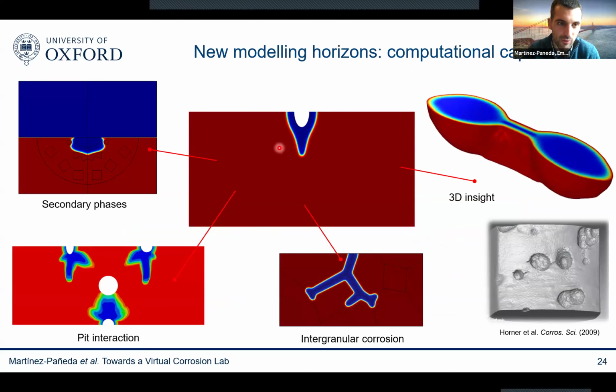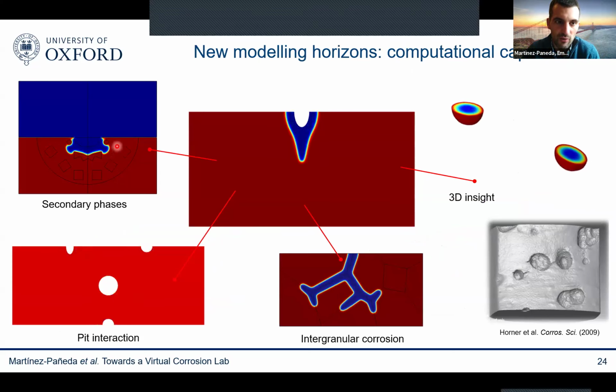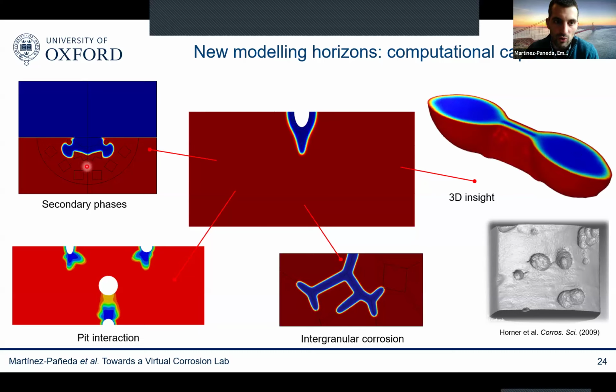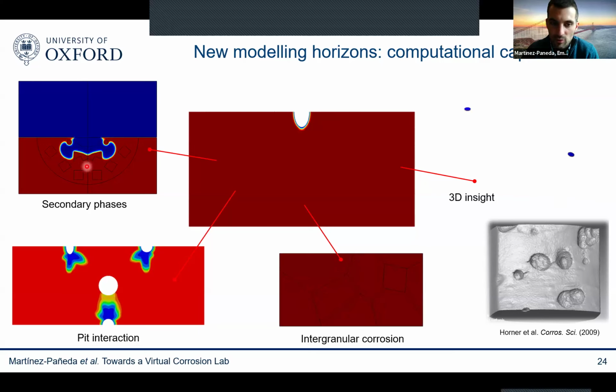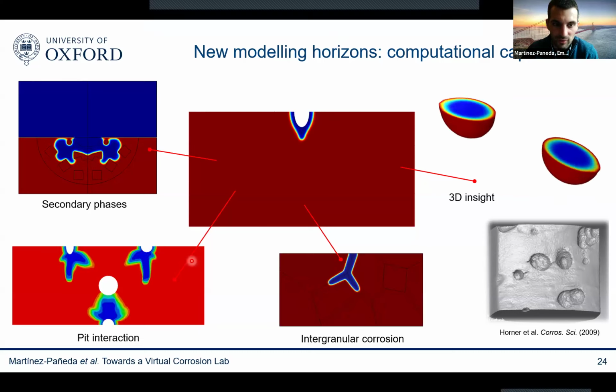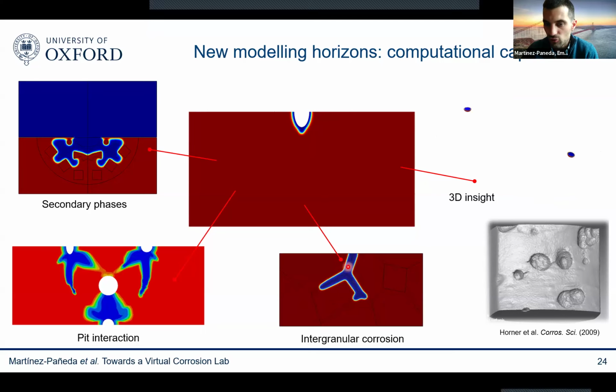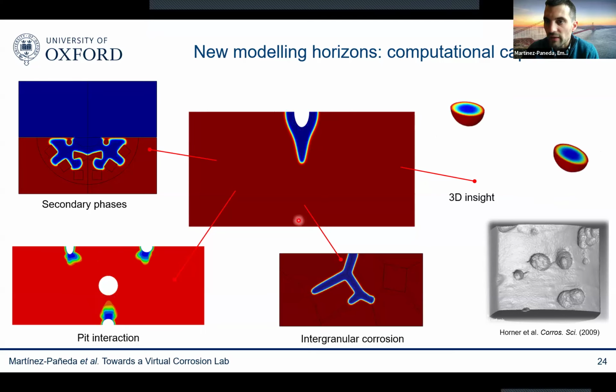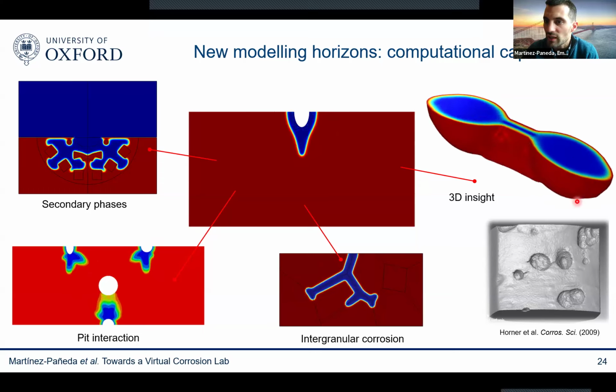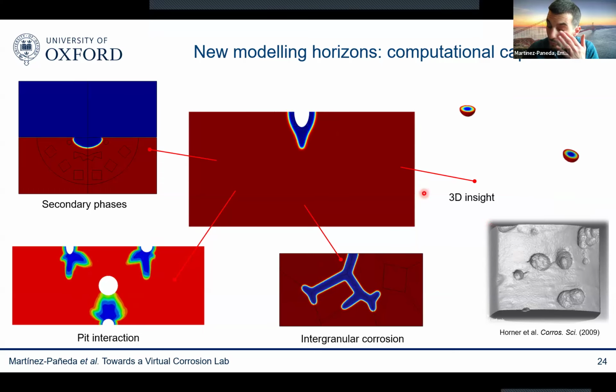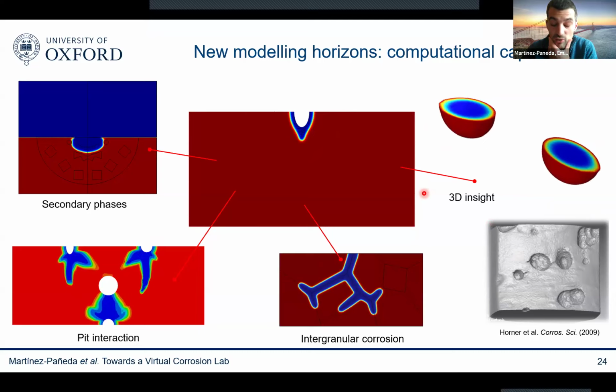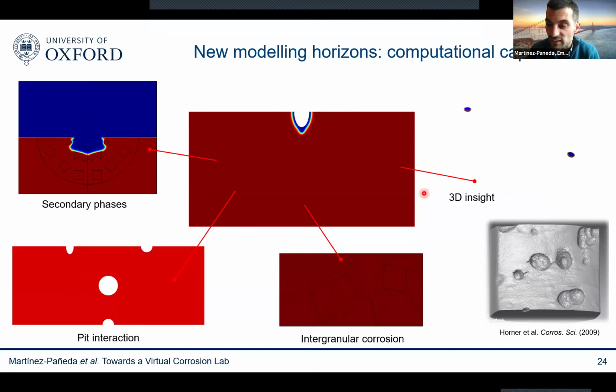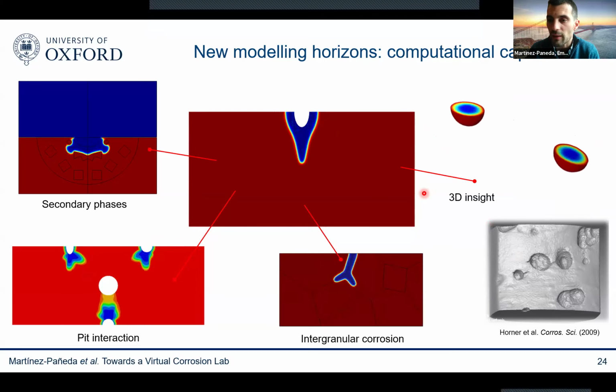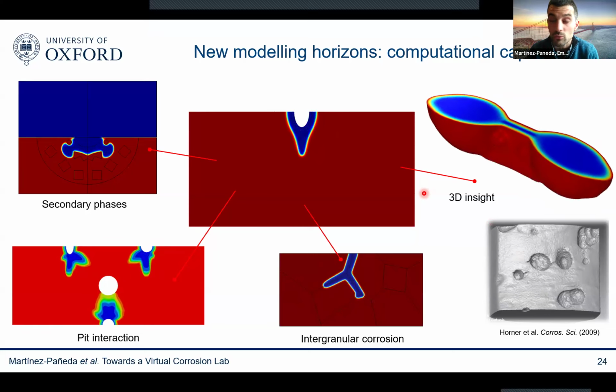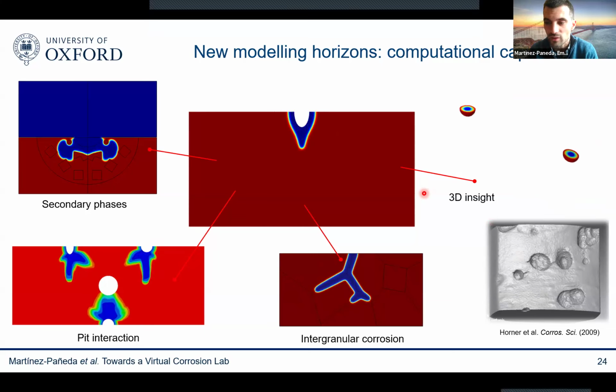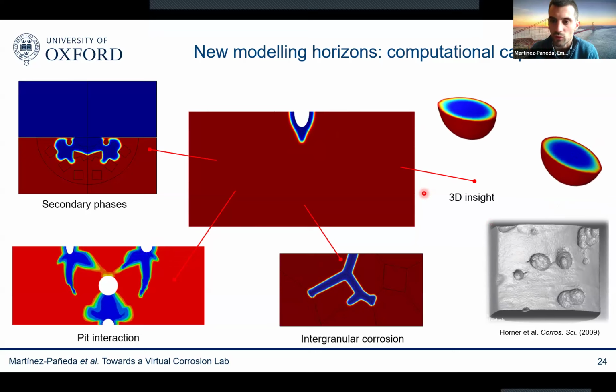So we can capture, for example, the role of secondary phases, how the corrosion front evolves to those insoluble secondary phases. I can capture the role of pit interaction without any arbitrary or ad hoc criteria. I can also capture intergranular corrosion. And of course, these simulations can be done in 2D and 3D. In fact, we have now recently compared our predictions with some new XCT synchrotron observations, and it has allowed us to rationalize some interesting observations that were made with those synchrotron measurements.